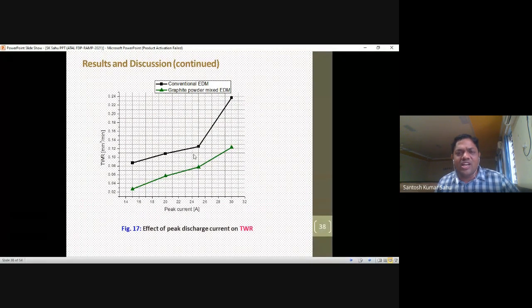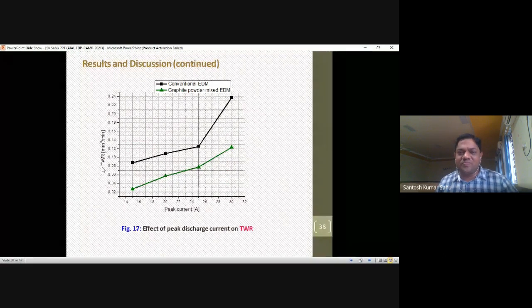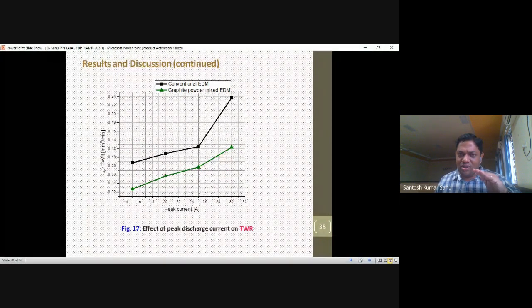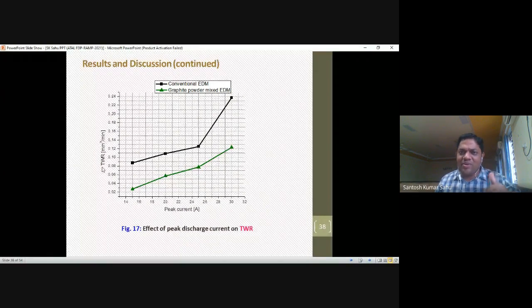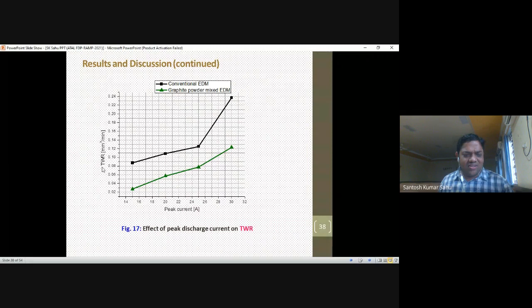The surface finish should not deteriorate because of the TWR, because we know that in the EDM process, the surface of the face of the tool is reflected onto our workpiece, and that should be very clean and have a good roughness value on your tool also. You can notice that here the tool wears sufficiently less compared to our conventional EDM. The tool wear rate is lessened, enhancing your tool life.